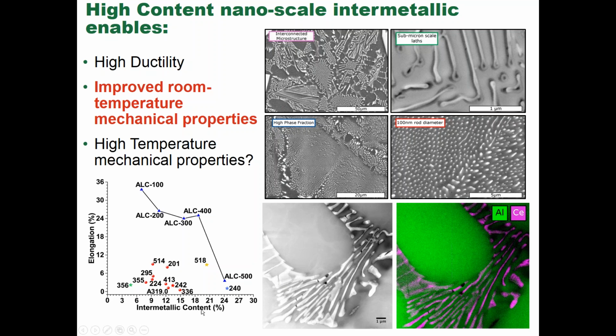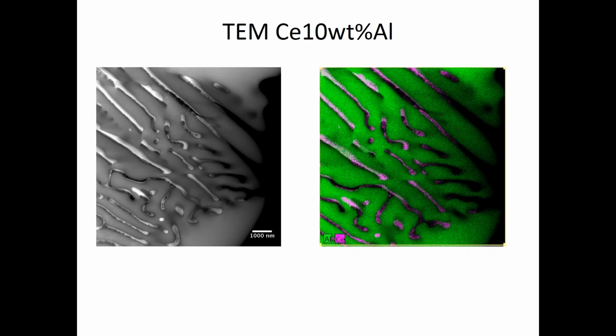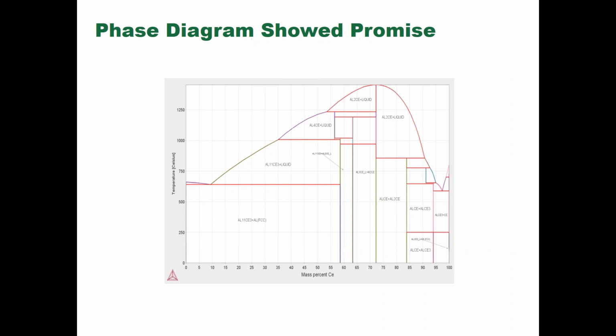In the lower left-hand side, you see the relative intermetallic content of some of the other alloys that are out there. These alloys do not have unusual amounts of intermetallics, but the intermetallics that are there are much more stable. So here's a TEM picture showing a little better that this microstructure is primarily an aluminum-cerium phase in an aluminum alloy. And you get an idea of the size. That's a 1,000 nanometer scale bar on the bottom, and pretty uniformly distributed through the alloy.